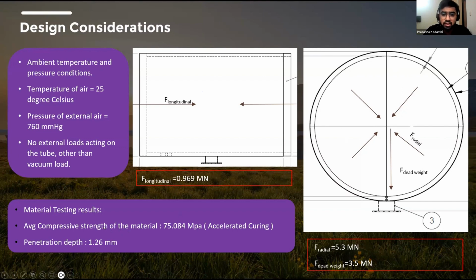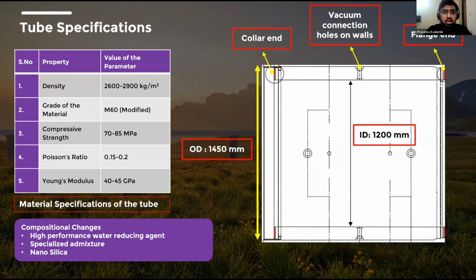So in terms of the material results that we observed from the lab scale prototypes that we had formed, an average compressive strength of the material that we observed was around 75 to 76 megapascals using the accelerated curing method. This is a 14-day strength that we have observed, with an average penetration depth of around 1.26 mm, which has been significantly reduced as compared to the ultra high performance concrete compositions that are readily available in the market and are currently being utilized. So we latched on to using those design considerations for the particular tube specification.